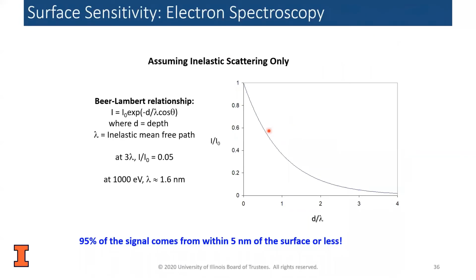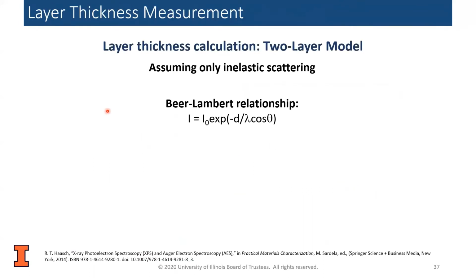And so on. Now I'm going to step aside a little bit and introduce to you a method for determining surface thickness. And so what we would like to do in our study is determine how the thickness of the alumina layer relates to the performance of the battery. And so if you use the Beer-Lambert relationship, which describes the attenuation of the electron as a function of depth, you'll see that we'll get this exponential decay. And then we can actually use this equation to develop a model to estimate the thickness.